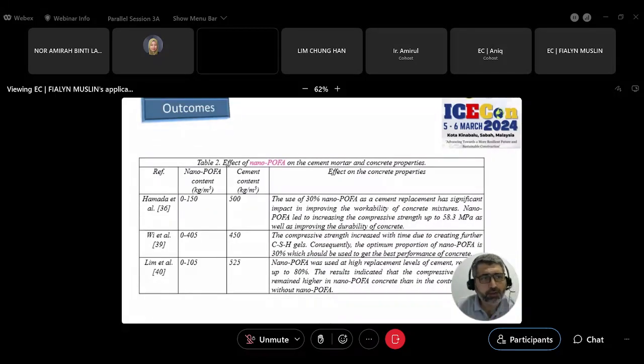Another outcome here is to show the effect of nano palm oil fuel ash, or POFA, on the cement, mortar, and concrete properties. Hamada et al., who is our postdoc here, actually used up to 150 kilograms per cubic meter of nano POFA content with cement content of up to 500 kilograms per cubic meter. They showed that the use of 30% nano POFA as a cement replacement has a significant impact in improving the workability of concrete mixtures.